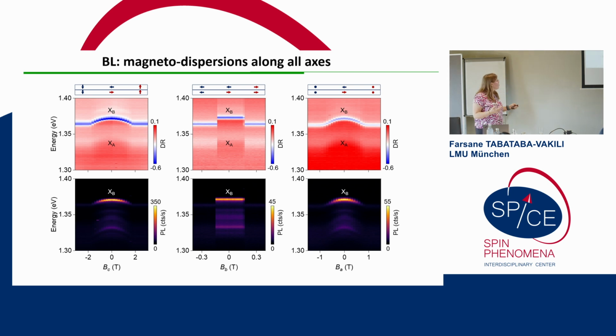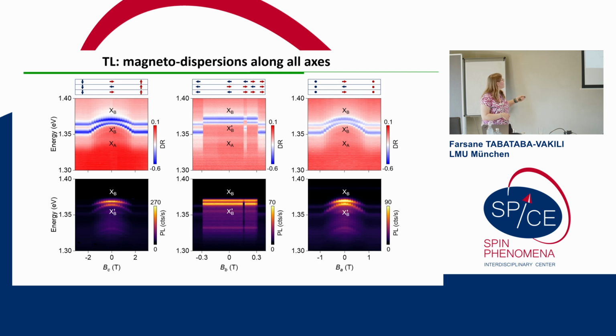And then in photoluminescence, we observe that in the antiferromagnetic state, the photoluminescence is very bright, but in the ferromagnetic state, it nearly vanishes, while the oscillator strength remains nearly identical. So it seems like the population relaxes into some dark state. Also quite curious. And similar things for the trilayer, just with a larger critical field along the B-axis of around 300 millitesla, and then this increases further as we go towards the bulk.